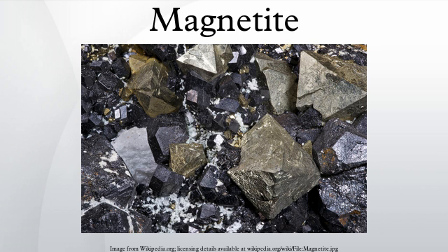Magnetite particles are of interest in bioscience applications such as in magnetic resonance imaging since iron oxide magnetite nanoparticles represent a non-toxic alternative to currently employed gadolinium-based contrast agents. However, due to lack of control over the specific transformations involved in the formation of the particles, truly superparamagnetic particles have not yet been prepared from magnetite. That is, magnetite nanoparticles that completely lose their permanent magnetic characteristic in the absence of an external magnetic field.